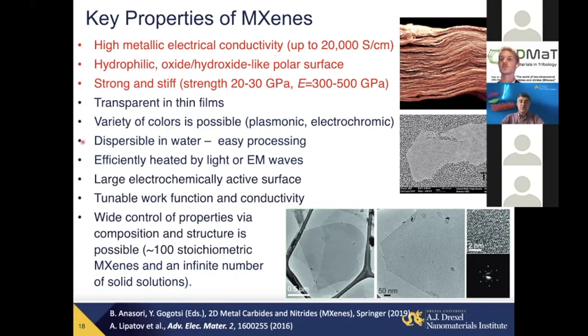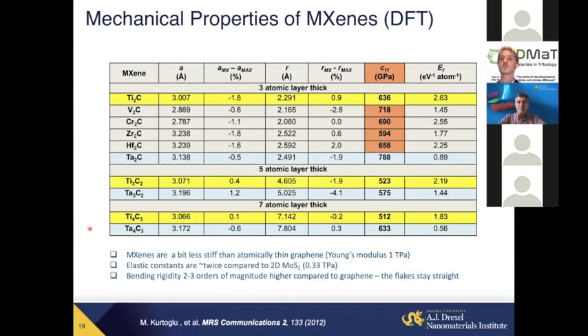And they are dispersible in water because they're hydrophilic, with these oxide surfaces. And again, what is important is wide control over properties. If you look at mechanical properties predicted for these materials, you will see Young's modulus being in the hundreds of GPa. It's a little bit lower than the in-plane modulus of graphene, which reaches a terapascal, like diamond. However, it's extremely high. Moreover, as I mentioned, stiffness is also higher. Bending rigidity is significantly higher for these materials, and it's definitely a high elastic constant compared to, say, the chalcogenides.